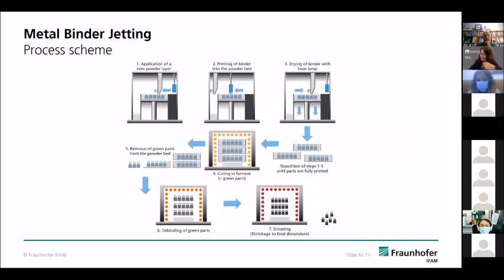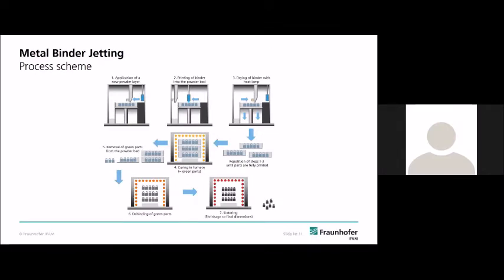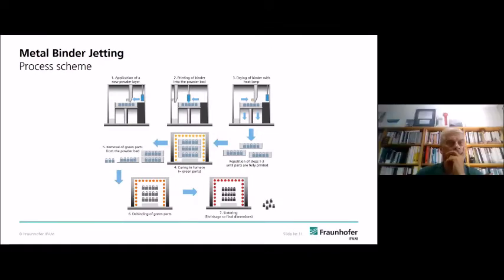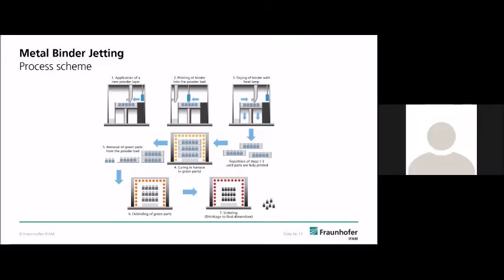So the first step of the metal binder process is to apply a powder layer as with the beam-based processes. So it's a powder bed-based process and a layer by layer build-up. In the second step, a binder is printed into the first powder layer. This binder is then cured by a heat lamp. And everywhere where you have binder in your powder bed, this is one layer of your part. And then these three steps are repeated. So powder layer, printing into the layer, heating the layer. And so layer by layer, you build up your three-dimensional part.